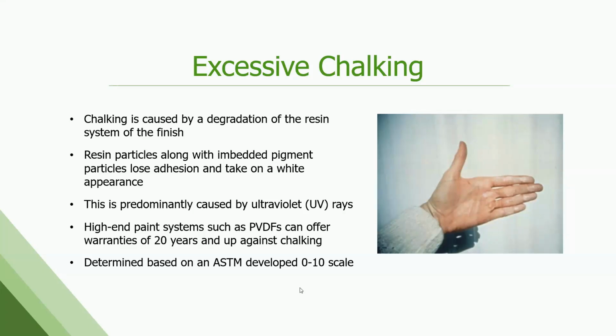There is an ASTM method for measuring this. It's a little bit subjective. You take a black rag, wipe it on the surface, you compare it to some photos, 0 to 10 scale. The higher the number, the better on this. So 10 means there's no chalking, and 8 means there's very little chalking. So that's kind of how the scale works. You want a higher number on this.